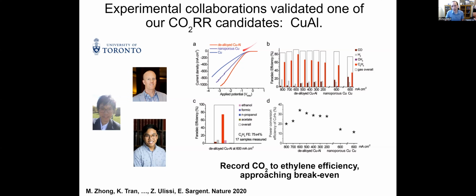This was particularly exciting because copper aluminum was not only found to be quite active for CO2 reduction, that's great. It was also found to be quite selective for ethylene out of all the possible C2 products. So at a specific current density of about 600 milliamps per square centimeter, it was making almost 80%, 75 or 80% Faraday efficiency ethylene. And ethylene is one of the most valuable building blocks that I could think of to make from CO2. So this was super exciting.